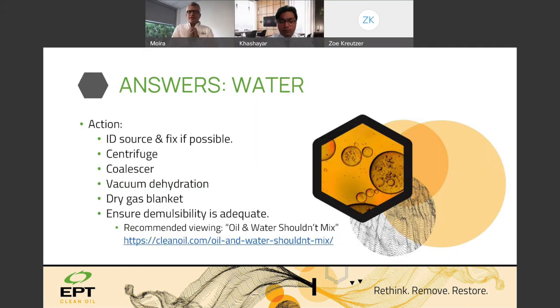We see a lot of centrifuges still used in water removal. Centrifuges would be ideally suited for higher water levels. Typically, the industry has moved to either vacuum dehydration or centrifuges for applications with high levels of water. For low levels of water, we'd use dry gas blankets.